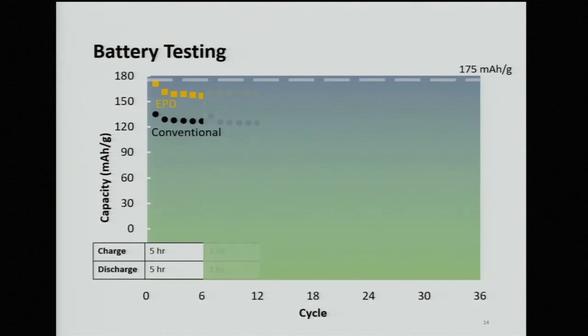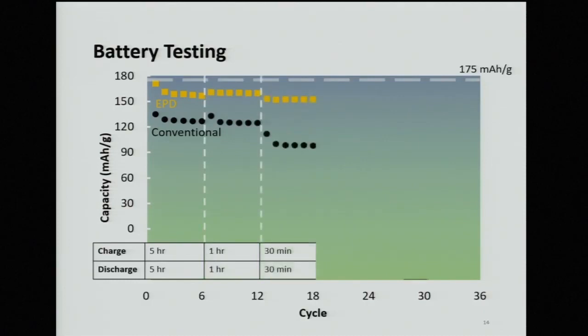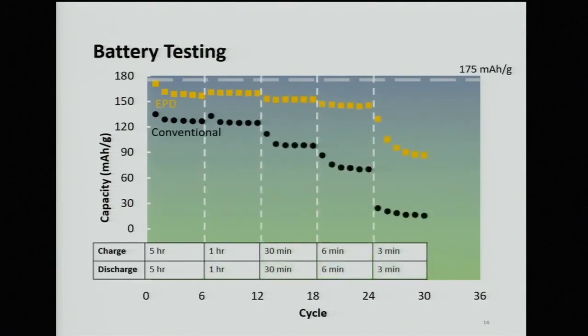So let's make it faster. Let's take 1 hour to charge and 1 hour to discharge. We see no difference. So let's speed it up even more. 30 minutes, 6 minutes, 3 minutes. Now we're really seeing a difference between the EPD and the conventional electrode. At 3 minutes, the conventional electrode capacity doesn't reach half of what the EPD does. So we can say that the EPD electrode performs better in fast rates. That's great. But now we need to know why.